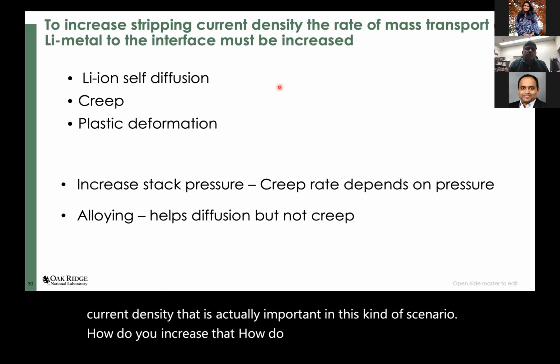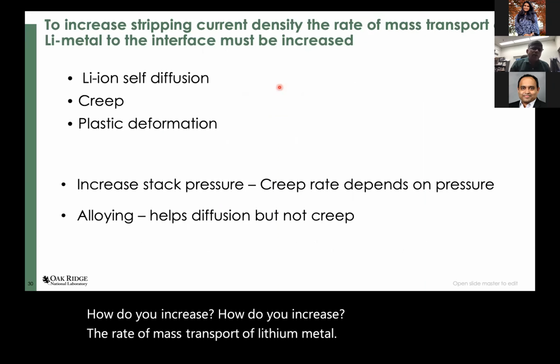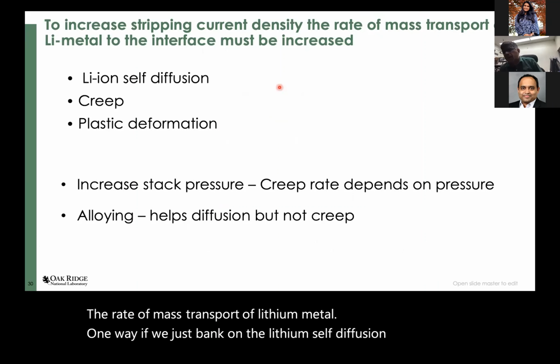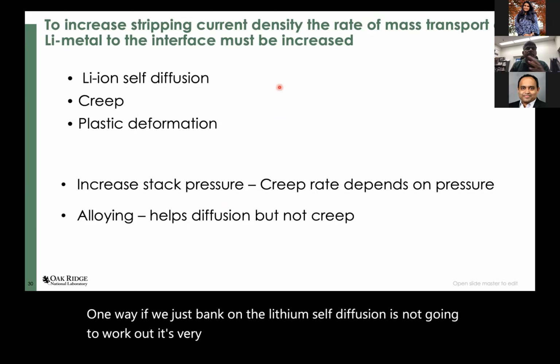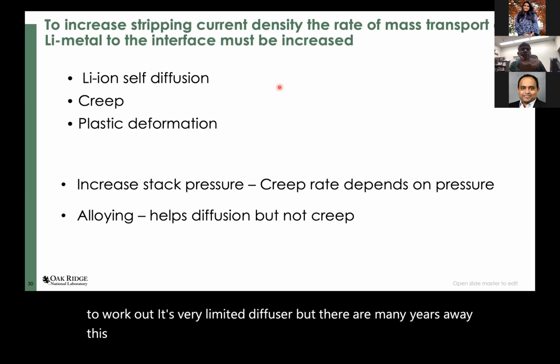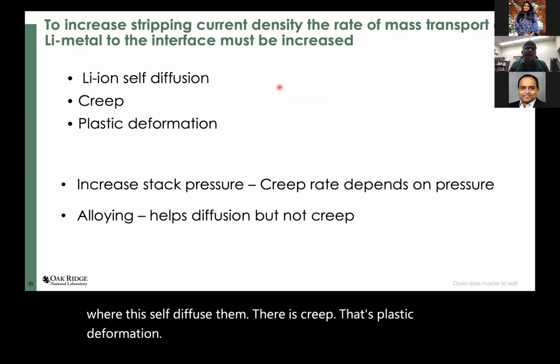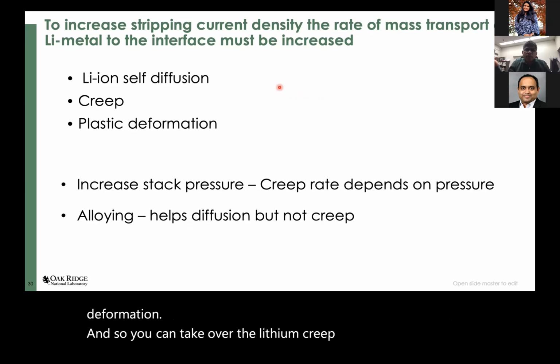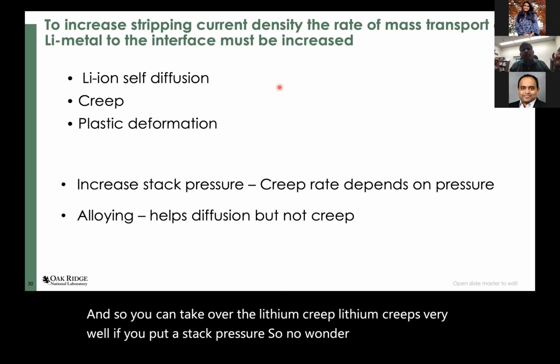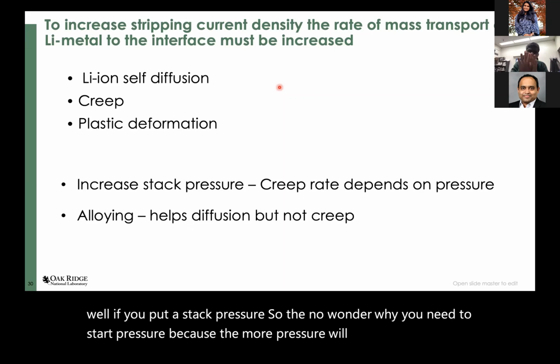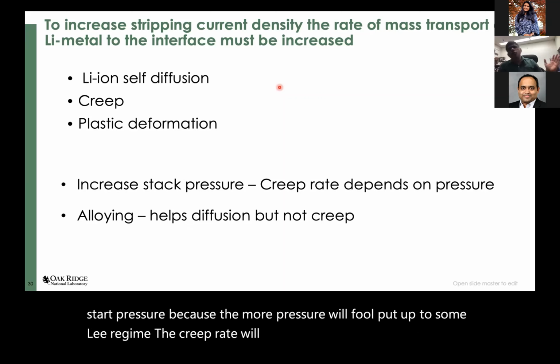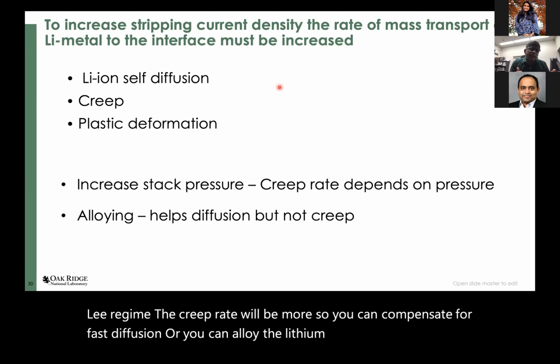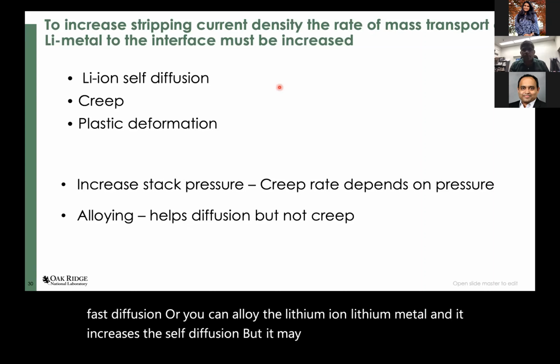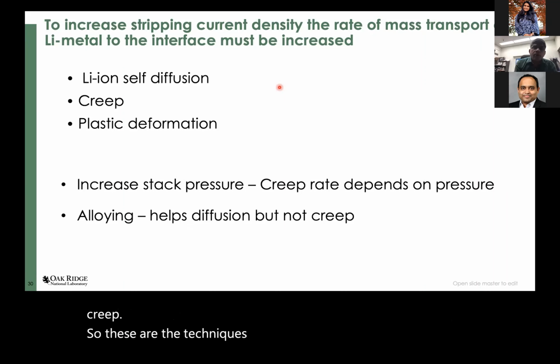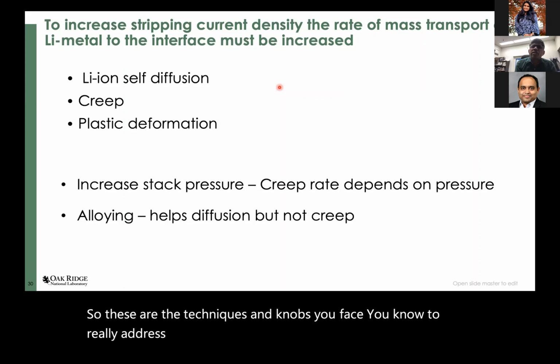So how do you increase that? How do you increase the rate of mass transport of lithium metal? One way, if you just bank on the lithium self-diffusion, it's not going to work out. It's such a very limited diffusion. But there are many ways: self-diffusion, there is creep, there's plastic deformation. And so you can take out the lithium by creep. Lithium creeps very well if you put a stack pressure. No wonder you need a stack pressure, because the more pressure you put up to some regime, the creep rate will be more. So you can compensate for fast diffusion. Or you can alloy the lithium metal, and it increases the self-diffusion, but it may not increase the creep. So these are the techniques and knobs you have to really address this rate of mass transport issue here.